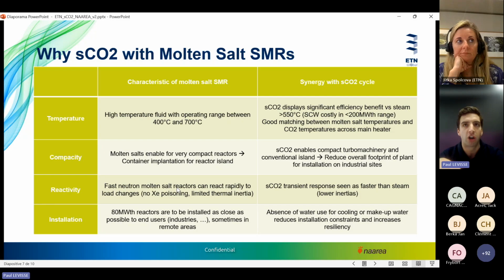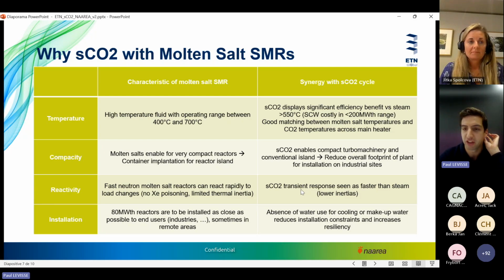If you're on a large steam cycle with large thicknesses, you don't get that reactivity, whereas the CO2 transient response is seen as faster than steam. It still has to be demonstrated, at least in situ in real plants, but we expect a benefit there.